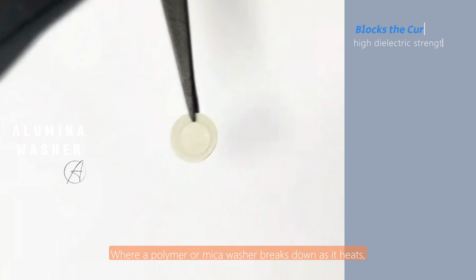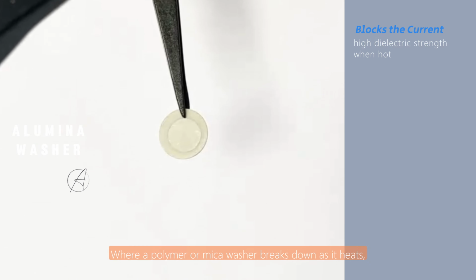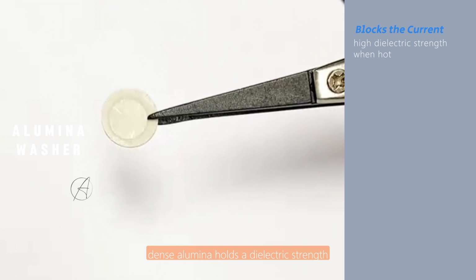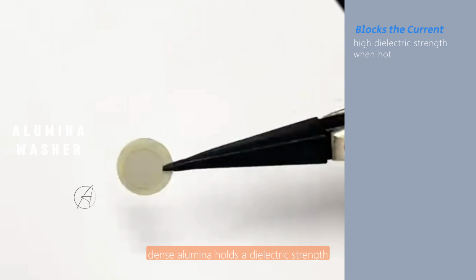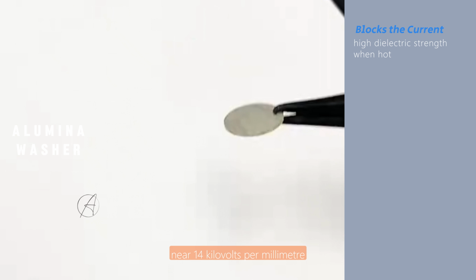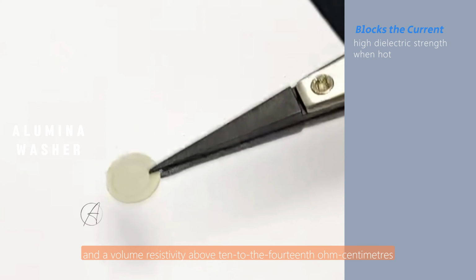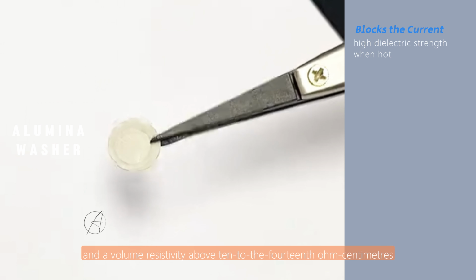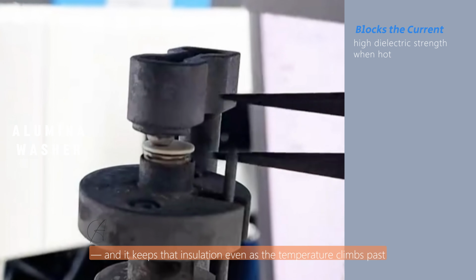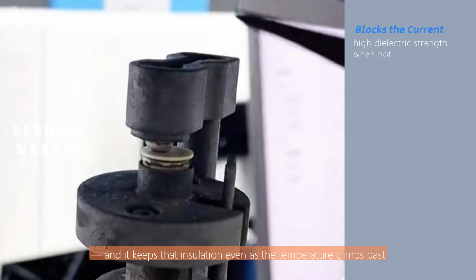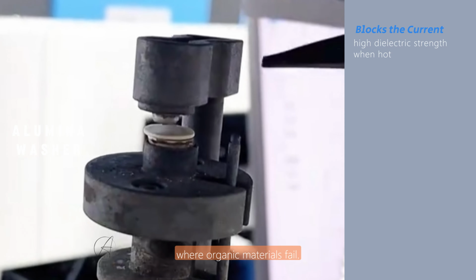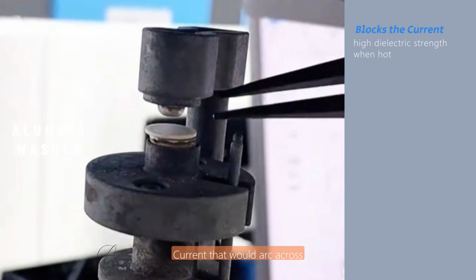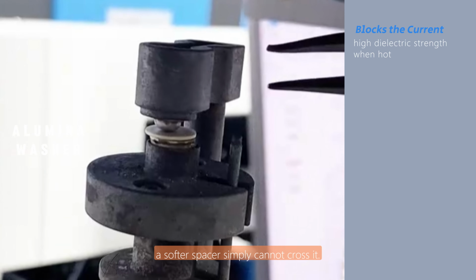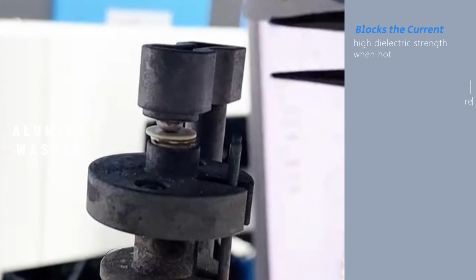First and foremost, it insulates. Where a polymer or mica washer breaks down as it heats, dense alumina holds a dielectric strength near 14 kV per millimeter and a volume resistivity above 10 to the 14th ohm-centimeters. And it keeps that insulation even as the temperature climbs past where organic materials fail. Current that would arc across a softer spacer simply cannot cross it.